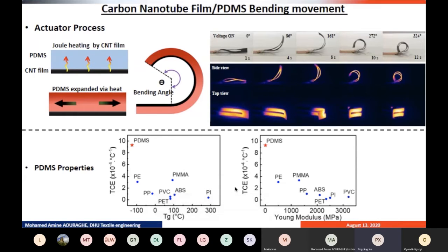Due to the high thermal conversion of CNT film, the heat is transferred directly to the PDMS, which expands under heat and leads to mechanical deformation and bending of the composites, as shown from the optical and thermal images. The mechanical movement is mainly due to the coefficient of thermal expansion mismatch between carbon nanotube film and PDMS. Among common polymers, the used PDMS has a great coefficient of thermal expansion and is a soft material, which leads to a large deformation.